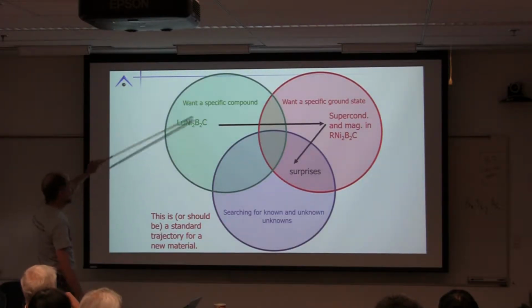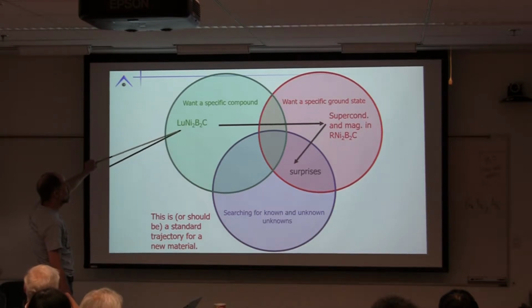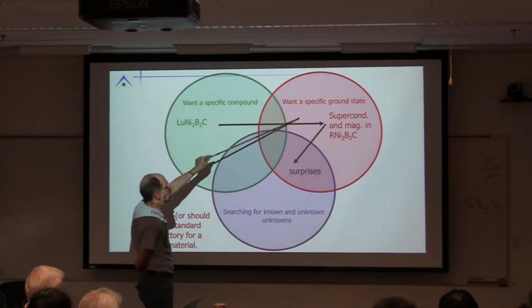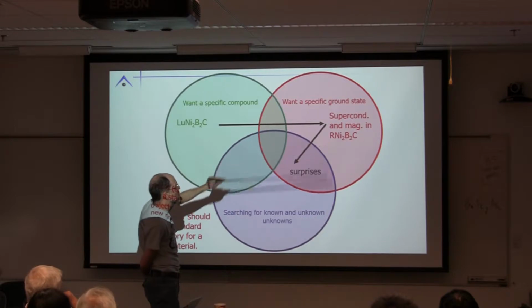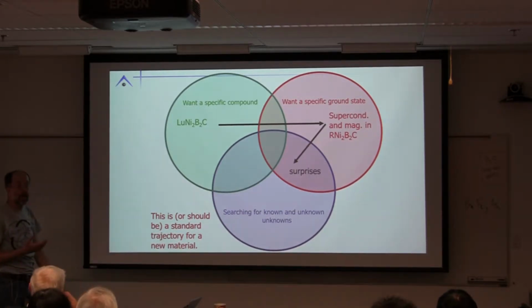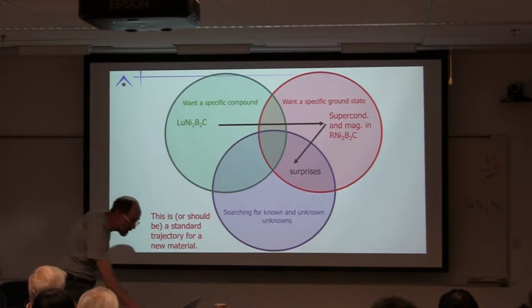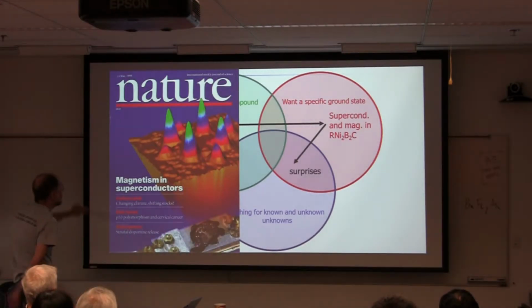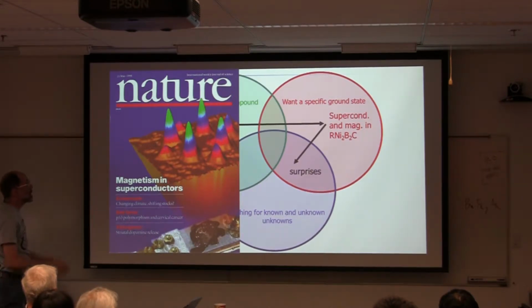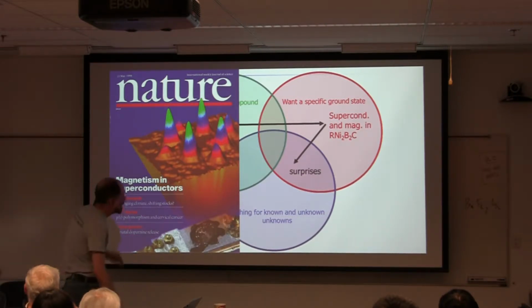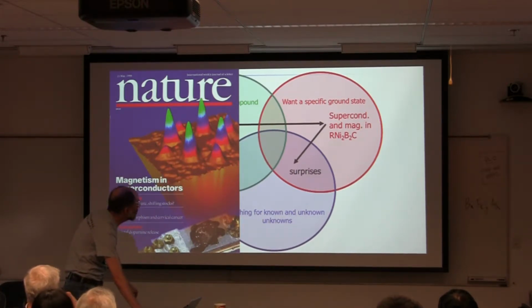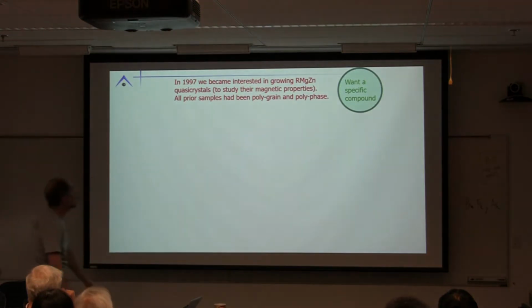So, we initially wanted a specific compound, lutetium nickel boron carbide. Then we wanted to explore specific ground state, superconductivity and magnetism in these materials. But then often when you play with new materials, you can run into surprises, either intentionally or accidentally. In this case, the surprise was these materials manifest some of the clearest examples of hexagonal to square vortex lattice transitions. Okay? And we could play around with those. So the point I want to make is you often have a sort of evolution from one of these motivations to another. Let's look at another example.